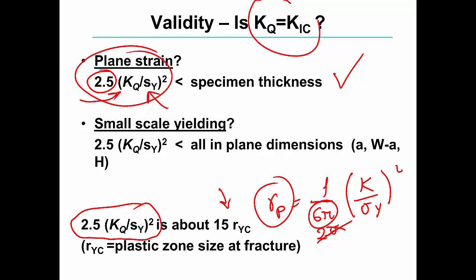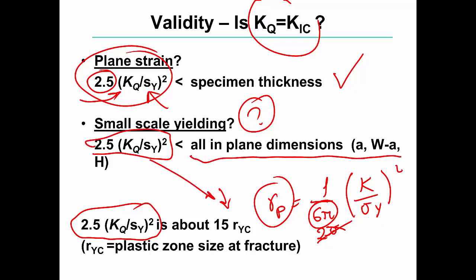But that's not enough. The next condition that we need to test is whether yielding around the crack tip is occurring at a sufficiently small scale. This is satisfied if the same value, which is proportional to the plastic zone, is smaller than all in-plane dimensions. I remind you that if the specimen is like this, this is my height, this is my width, and this is my crack size. Essentially this, that, they should all be much larger than this expression here. If that is true, it means the plastic zone at the crack tip is small enough, and that gives full validity, together with plane strain, to the value of the fracture toughness.